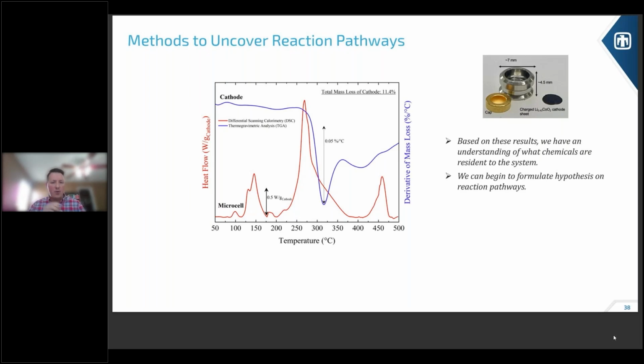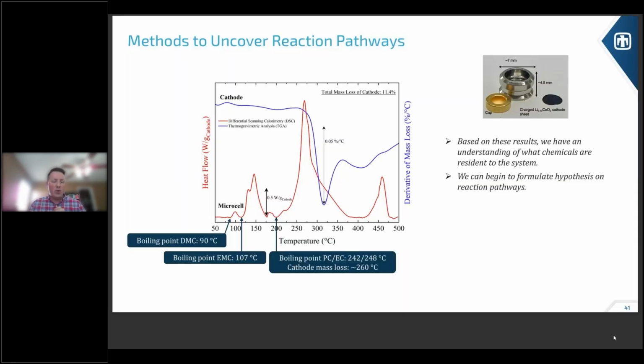So if you go ahead and go, I think four slide transitions forward, I'll just talk through. So this first point is the boiling point of DMC. It's at 90 degrees C. Right after that boiling point, you see this kind of red curve. That's a heat flow. And then we have boiling point of EMC at 107. Right after that point, you see another bump in the red curve that's larger. That's a larger heat flow. And then at 200 degrees C, we have boiling point of PC, EC, and within this largest red hill here, we have cathode mass loss.